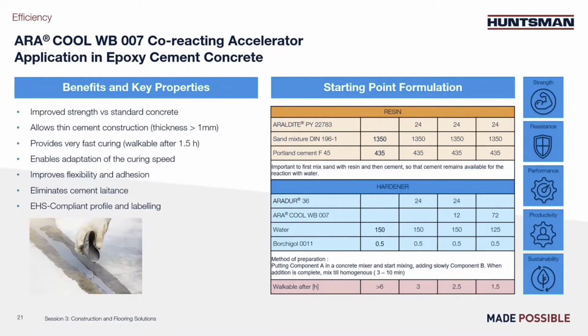In the last two columns, we are adding or substituting completely Aradur 36 by Aracool waterborne 007, and you can see that reaction is accelerated. So the new Aracool waterborne 007 allows to create a faster epoxy cement concrete. It improves flexibility and adhesion and avoids cement laitance. Viscosity can be adjusted depending on the quantity of cement and the water used, of course.